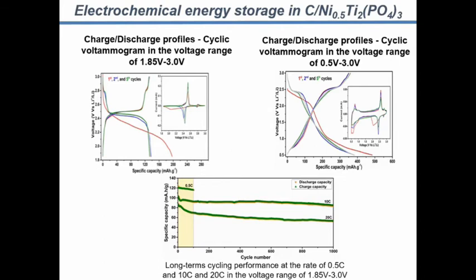So we performed the test in two windows. The first one in the voltage window between 1.85 to 3 volt, and the second one between 0.5 and 3 volt. And you can see that in both cases we have a good reversibility of the insertion extraction process. During charge and discharge, we got 130 milliampere hour per gram in the first window, but we can reach more than 350 milliampere hour per gram during the first cycles.